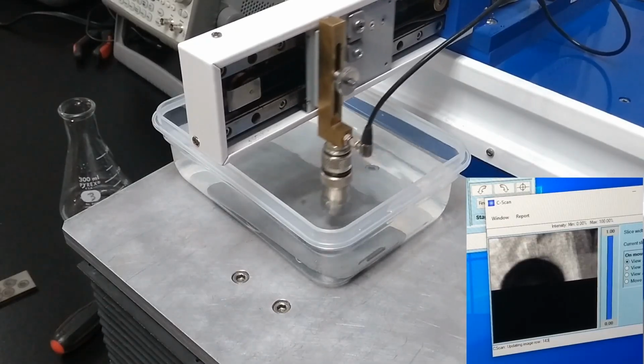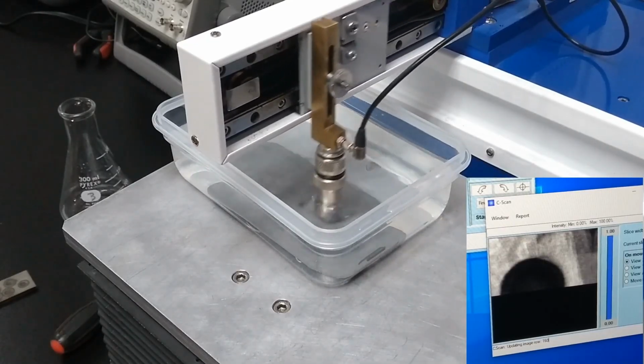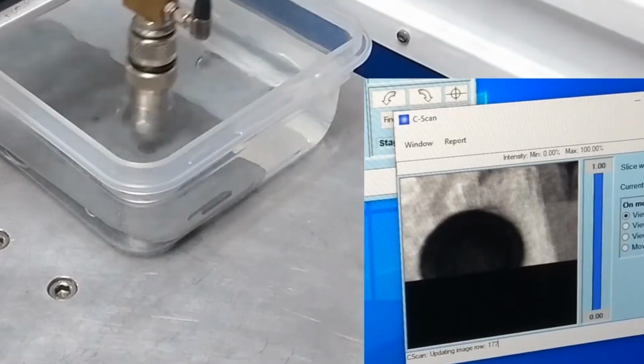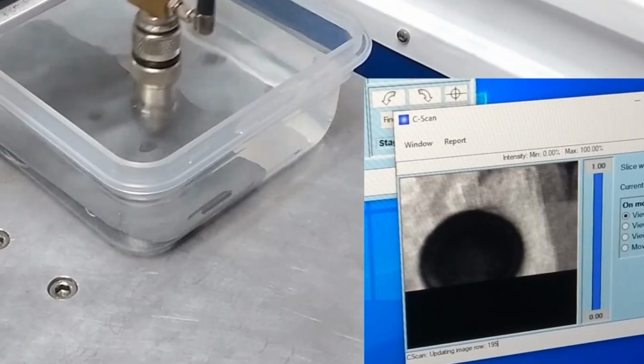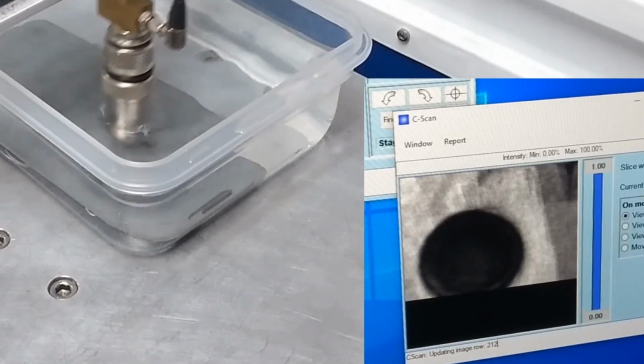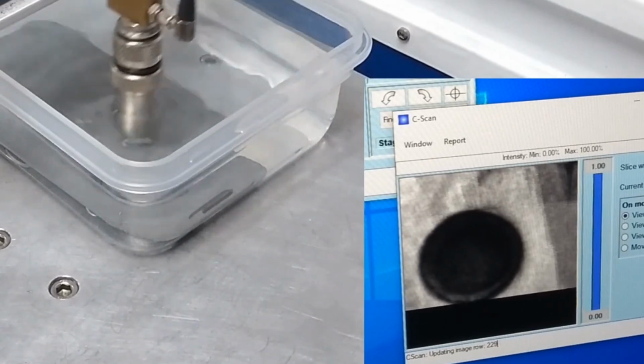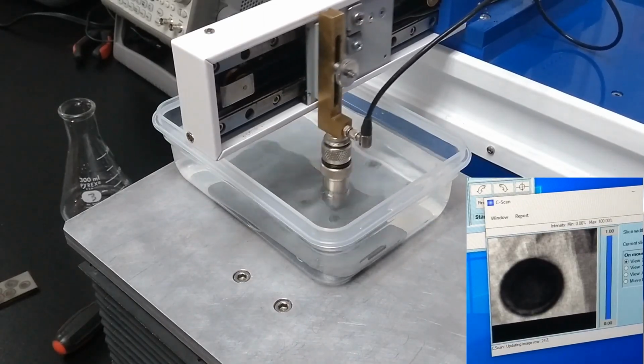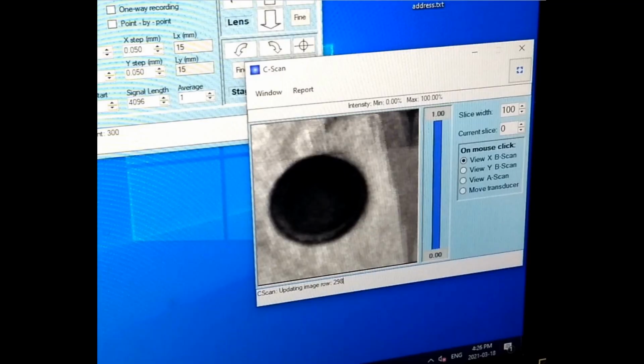Once completed, the C-scan will give a visual representation of the spot weld. The dark black circular area is the nugget, while the lighter area surrounding it is the unfused plates. Since we know the size of the work area, 15 by 15 millimeters, we can directly measure the size of the nugget from this image.